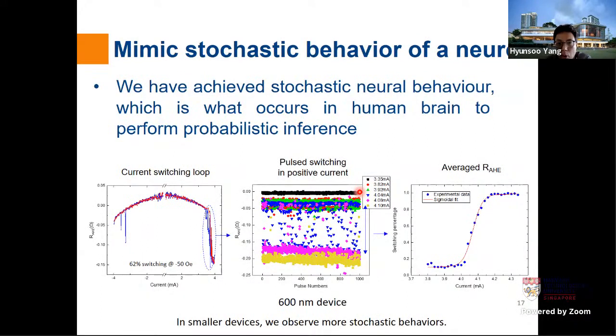Now we give more pulses. This is basically the pulse-based switching. So we give more pulses at a certain amplitude. You can see the blue one, 4.04 milliamp pulses. The blue ones fluctuate from here to here, and we have many intermediate values. If you apply 4.1 milliamps, that is the yellow one, you can see it's already fully switched, and it maintains the saturated value.